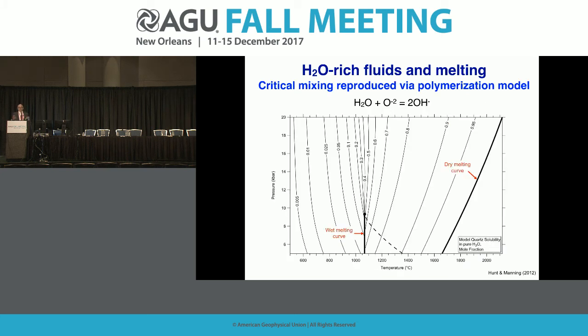We can use the fact that this polymerization is happening to build a thermodynamic model for the system SiO2-H2O using an approach that Ed Stolper used some years ago, just looking at basically the interaction between a bridging oxygen position in a silicate material and molecular H2O with two hydroxyls.